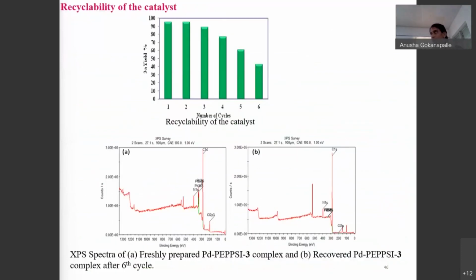Recyclability of catalyst. I have recycled the palladium PEPPSI complexes and checked for C-arylation reactions. We observed dropping yields. We have observed up to 6 cycles. After 6 cycles, leaching of palladium catalyst was observed. That is why we did not get more yields.